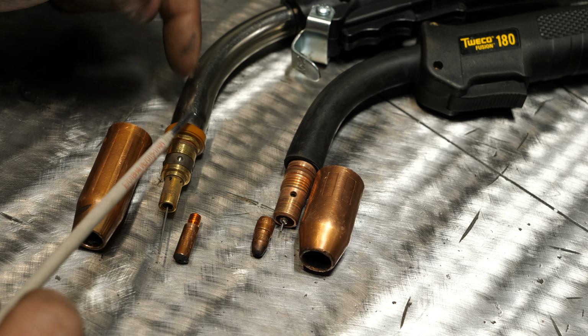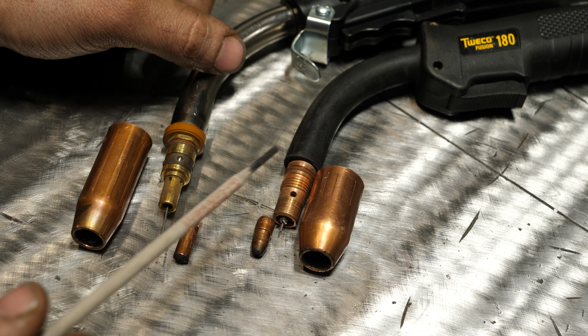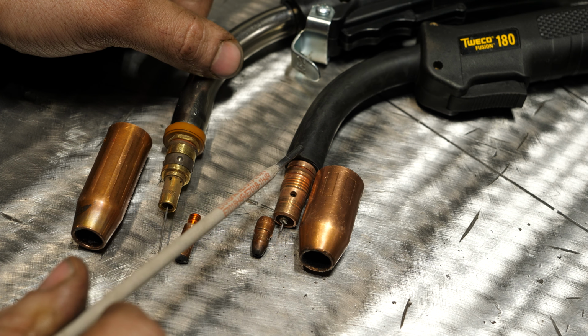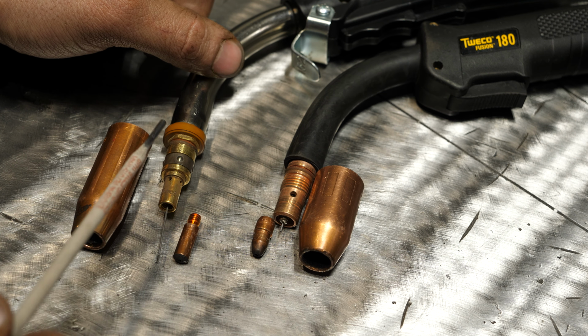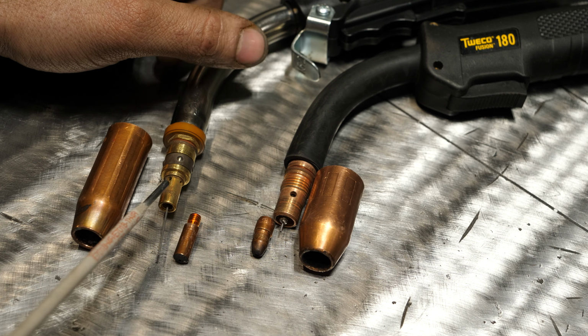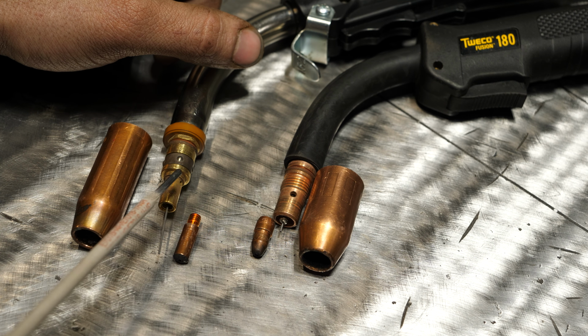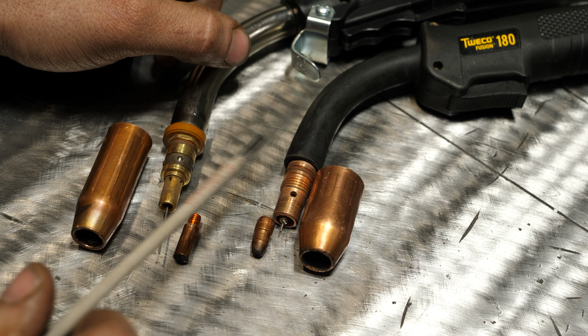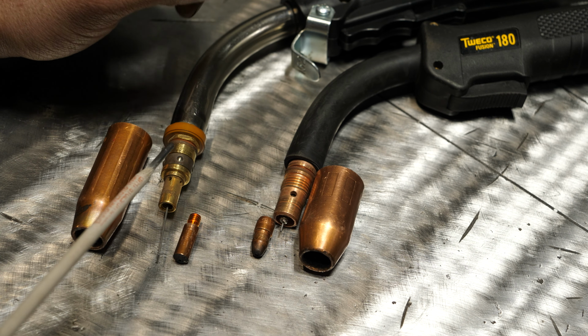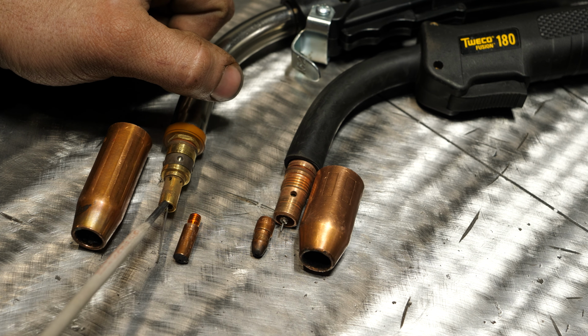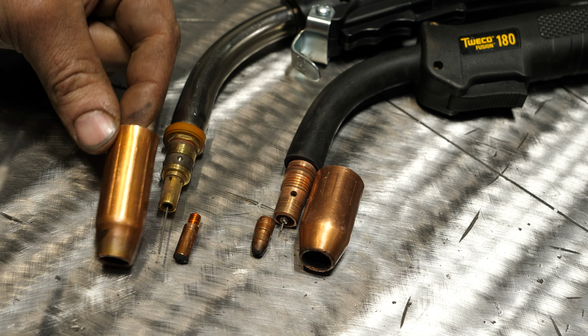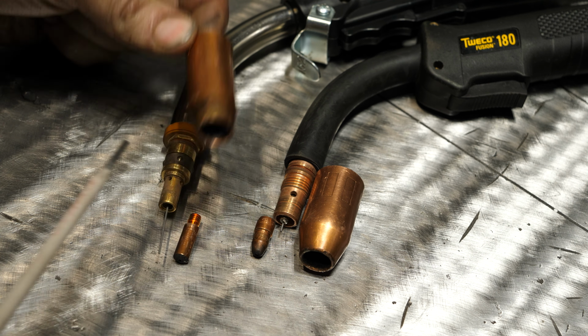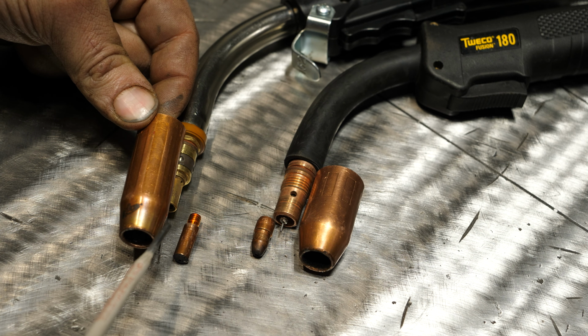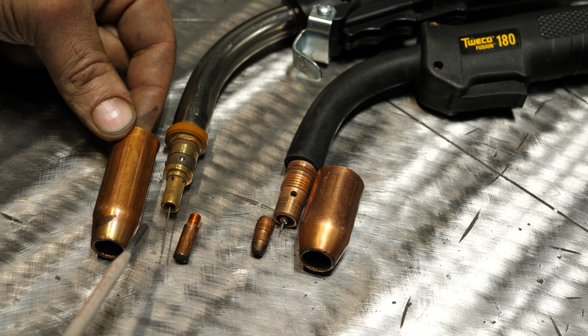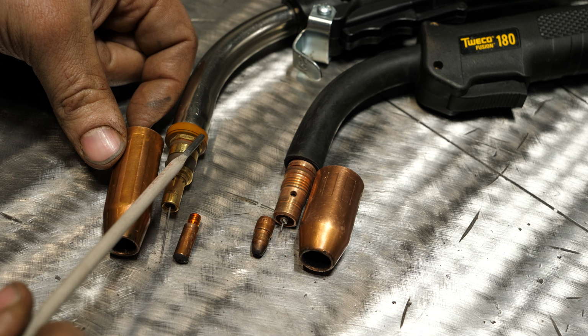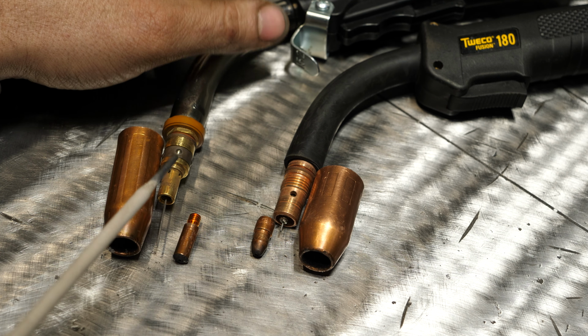And that's one of the reasons why this is stainless steel on the neck and this is like some form of rubber. If you were to put a rubber neck on this and try and run 230 amps and spray for a while, this will set on fire or start dripping. And that's why you don't typically see that kind of a neck on a spray gun and why everything pushes the heat so far out. Even the nozzle, you can see contacts way back here, yet the heat is this far up. And that's to help dissipate that heat and not let the heat get to the components up here and cause failures.